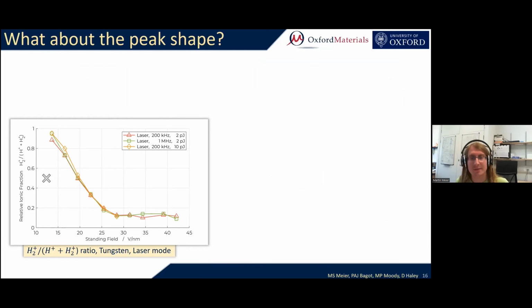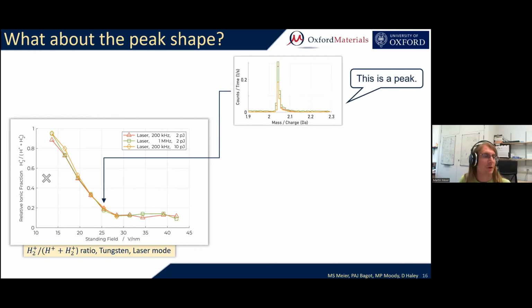The second observation that we can make is concerning the peak shape. And what we find is the following. On this falling slope of the diagram, so this part where the hydrogen has the behavior of what we would call the normal behavior, the peak shapes are also the very normal peak shapes that we usually see. So what you see here is the mass charge 2 peak closely zoomed in, and we confirm this is a peak, this is what a peak looks like, and so far so boring.